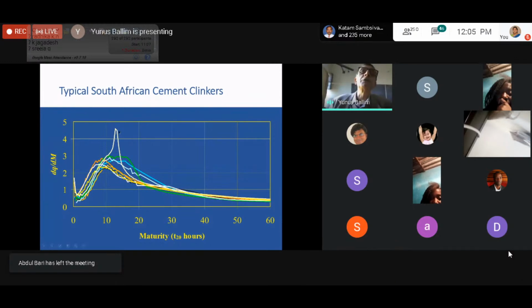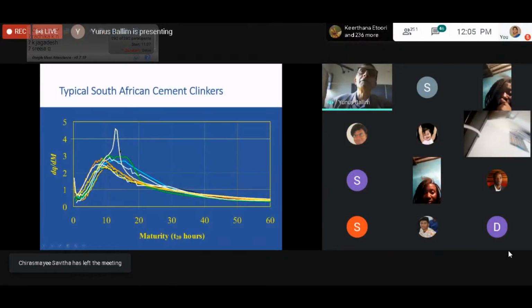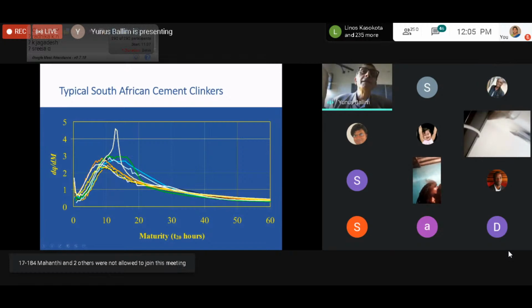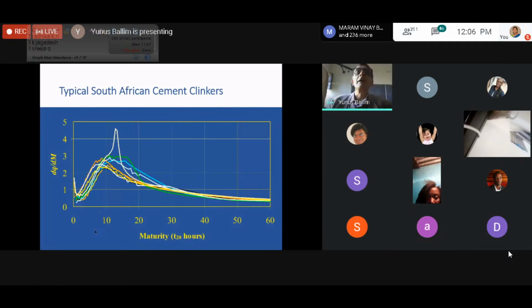This one that happens to stand out just has a particularly larger amount of magnesium in it, periclase. But otherwise, you can see that the peak heat rates occur at different times for different durations, and they heat and cool at very different rates. So when you buy something called Portland cement, don't imagine that they're all the same thing.